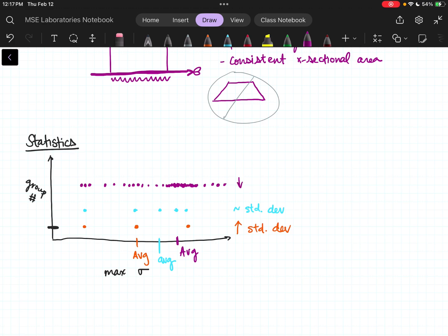So now we can see that my average is here. I still have a standard deviation, but I'm going to have a much lower standard deviation because I have so many points right around my average. You don't have to draw 40 points, but the idea is you can see very clearly I've got these clusters. Probably some of my specimens had scratches on them, and I can see a little cluster down here. I've also got a little cluster here, and that cluster lines up with the average of the orange group. So those were probably the internal problem specimens. I have a couple of those, but on average, most of my specimens don't have any issues.